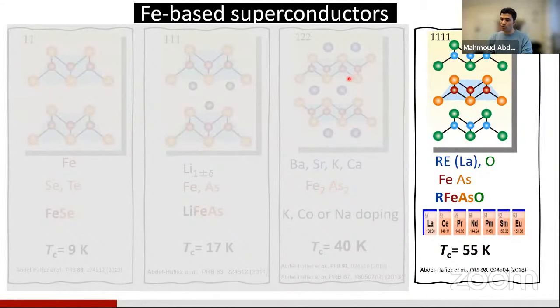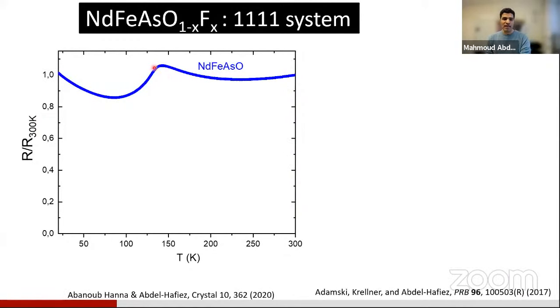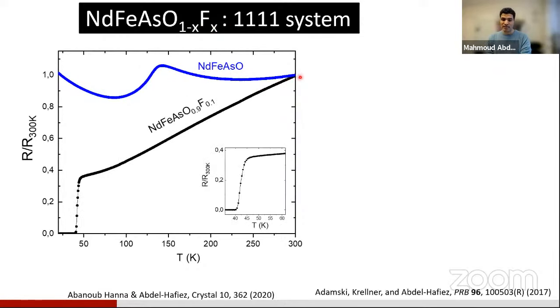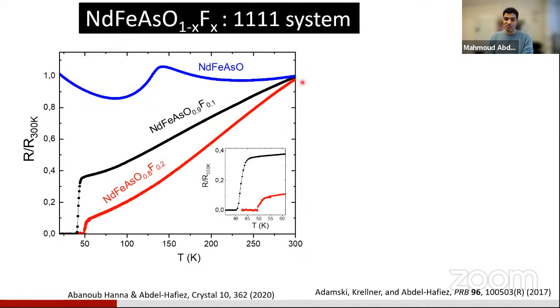And the last system I want to show is related to the 1111 compound, which shows the highest TC in this class of family. By measuring neodymium iron arsenic oxygen, you can see here no superconductivity at all. What you see here is the magnetism. So now we try to dope the system with fluorine, adding fluorine on the oxygen site. What we have seen here is very nice metallic behavior, and you can see the drop here to zero. That's an indication of superconductivity. If I increase the doping more, the TC goes up to 55 Kelvin. So that's a way we enhance the superconductivity in this class of materials.